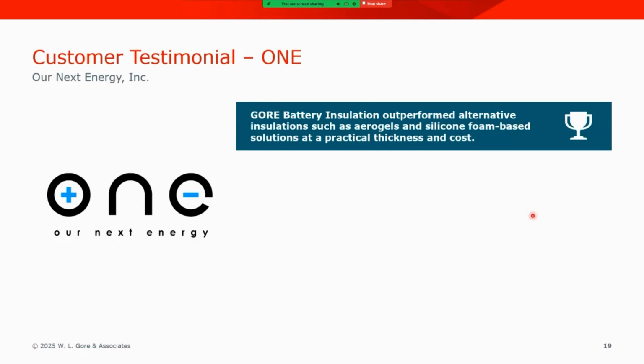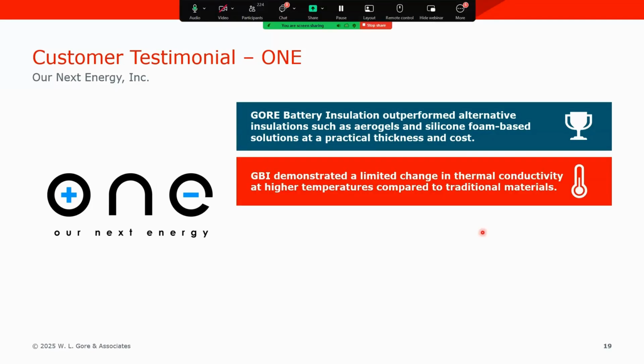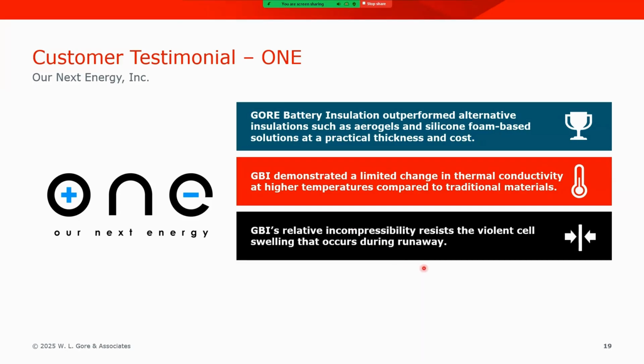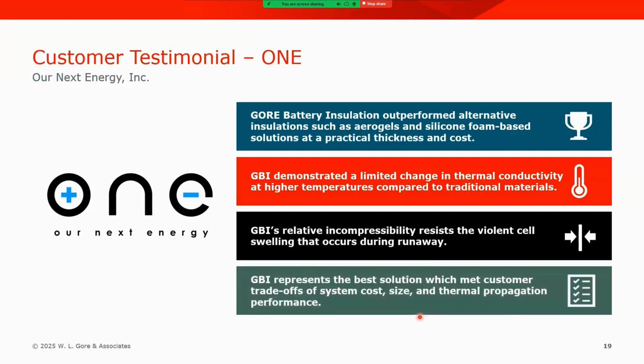And their conclusions are as follows: that the GORE battery insulation outperformed alternative insulations such as aerogels and silicone foam-based solutions, especially at a practical thickness and cost. And remember, thickness is what leads to energy density. Secondly, that the GBI material demonstrated a limited change in thermal conductivity, especially at higher temperatures. Its relative incompressibility resisted the violent cell swelling that occurred during thermal runaway. And finally, that GBI represented the best solution which met the customer trade-offs of cost, size, and thermal propagation performance.